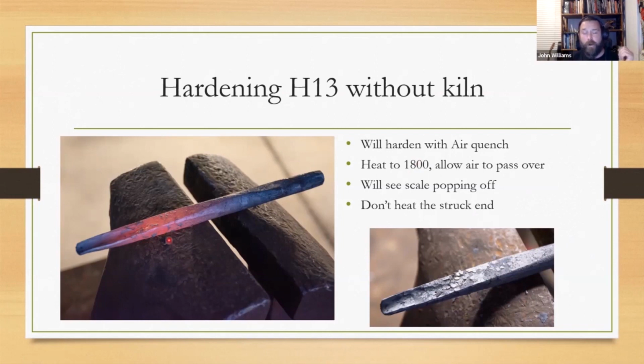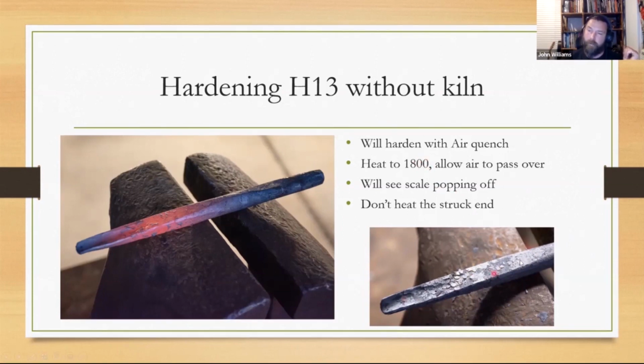So you can start to ramp it up, but you'll know that it's hardening with H13 if the scale starts to pop off. So scale popping off is a good indication that you're forming martensite. And you always want to have safety glasses when you're working with this steel, because this stuff will fly. But if you don't bring it up to critical temperature and it doesn't have the scale pop off, remember the color that you did, and don't take it all the way up to what you think is 1800 and then just try to guess at it. Get it a little bit hotter, like a shade hotter than what you would do for normal steel, and then let it air harden. If you see that scale pop off, test it with a file, see if it's hard. And then if it's not, put it back in the forge. It won't hurt it. Bring it up another shade past that.